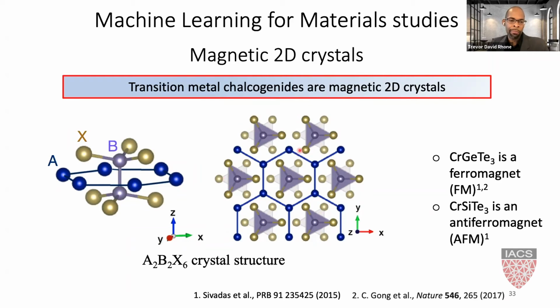You take a part of the crystal, and you see that the A sites form this hexagonal lattice, decorated by the B site in the center of that hexagon, and 3 tellurium atoms or X sites above and 3 below the plane. Now, something interesting happens when you change the germanium site, the B site, to silicon. You find that the lattice becomes anti-ferromagnetic.